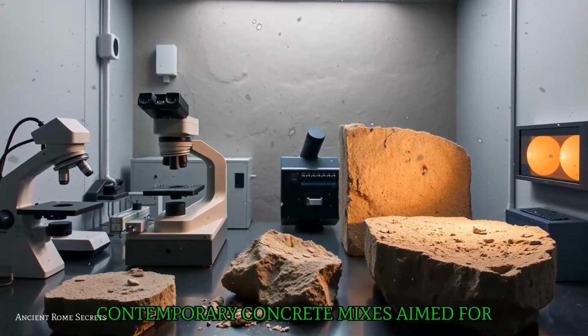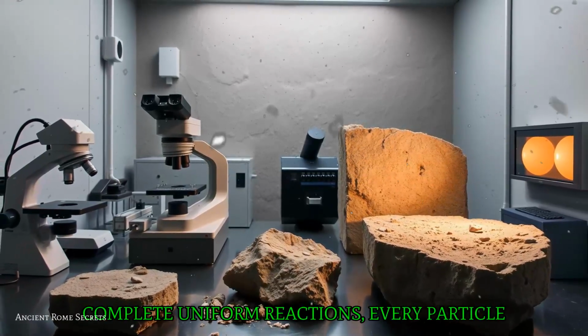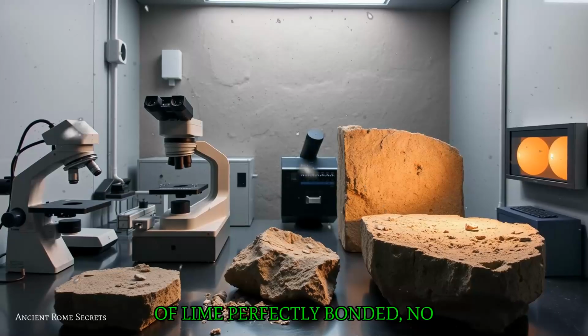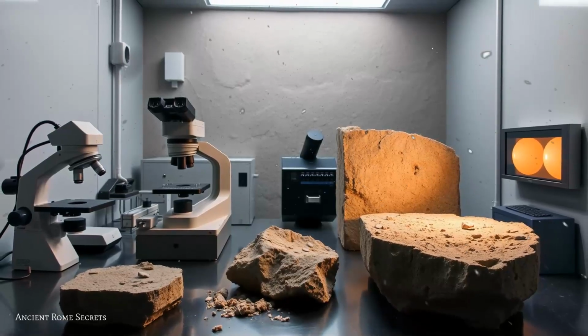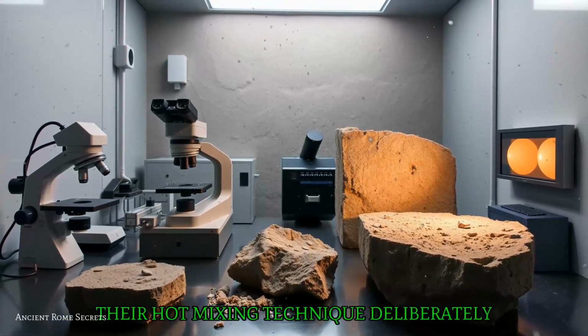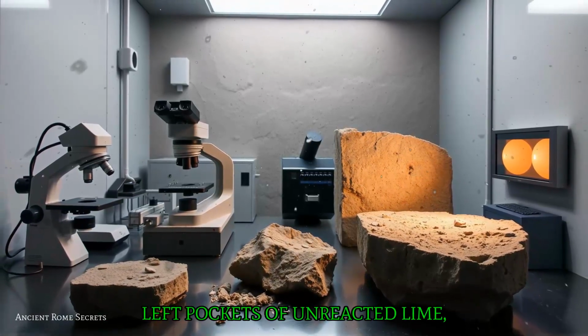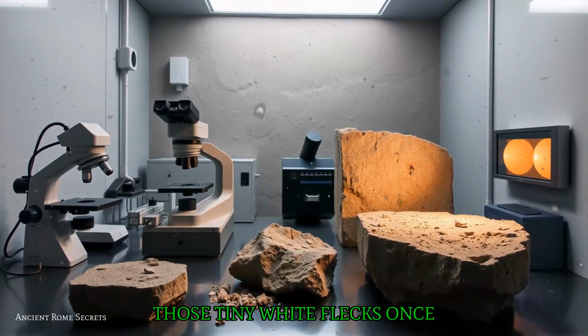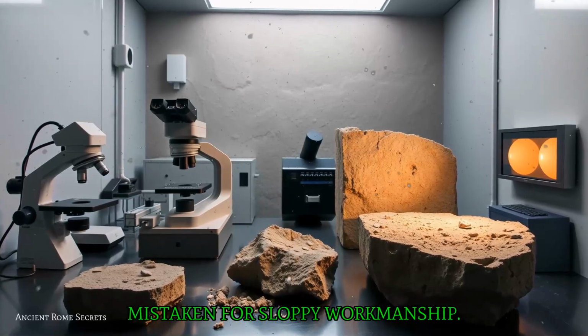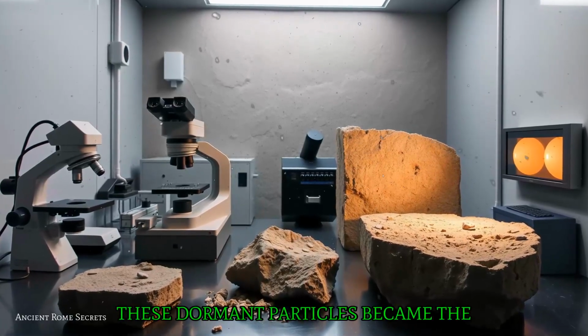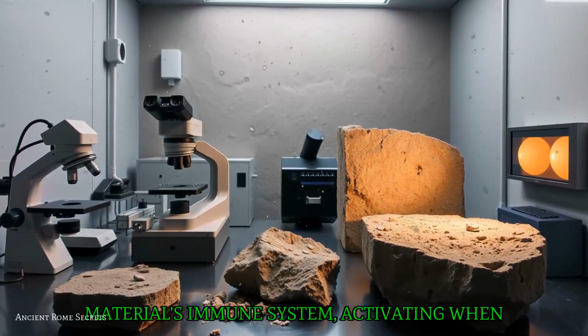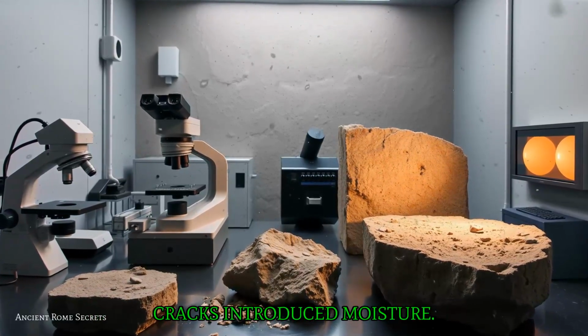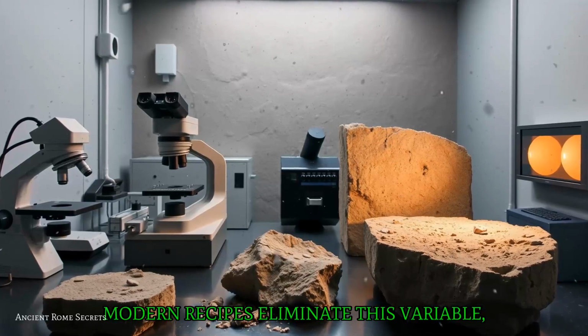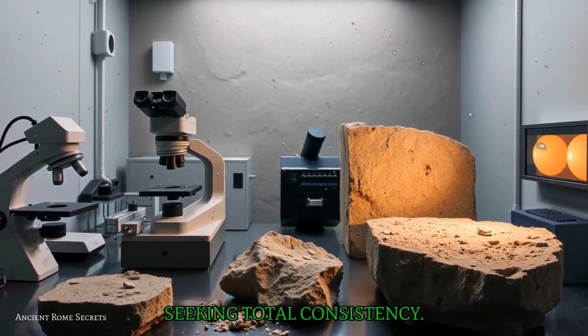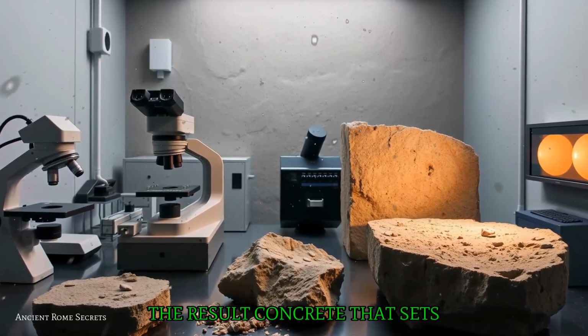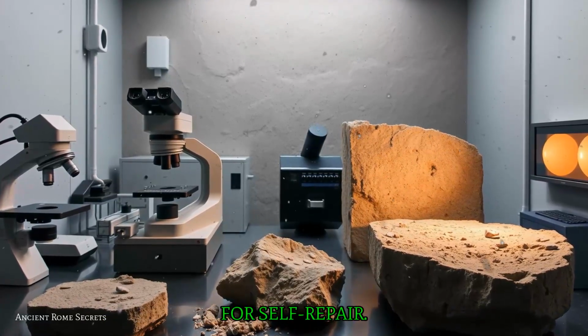Contemporary concrete mixes aim for complete, uniform reactions, every particle of lime perfectly bonded, no remnants left behind. Roman engineers did the opposite. Their hot mixing technique deliberately left pockets of unreacted lime, those tiny white flecks once mistaken for sloppy workmanship. These dormant particles became the material's immune system, activating when cracks introduced moisture. Modern recipes eliminate this variable, seeking total consistency. The result: concrete that sets predictably but has no capacity for self-repair.